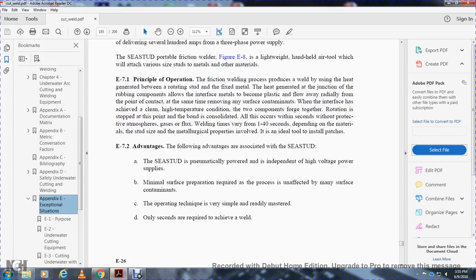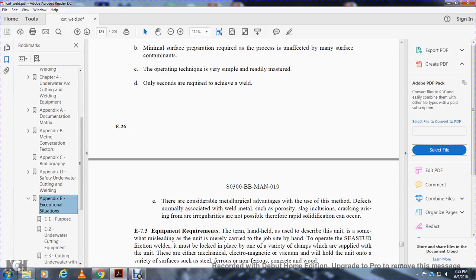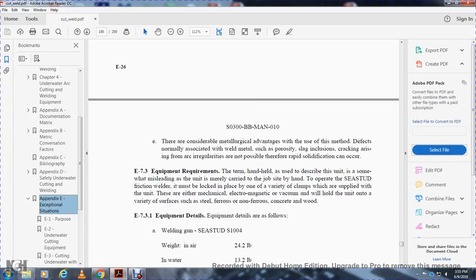Alright, E72, advantages. The following advantages are associated with the SEASTUD. A, the SEASTUD is pneumatically powered, independent of high voltage power supplies. B, minimum surface preparation is required for the process, and it is unaffected by contamination of the main surface. C, the operating technique is very simple and readily mastered. D, only seconds are required to achieve the weld. E, there are considerable metallurgical advantages, with the method avoiding defects normally associated with welded metal, such as porosity, slag inclusion, and cracking arising from arc irregularities are not possible, therefore rapid solidification can occur.